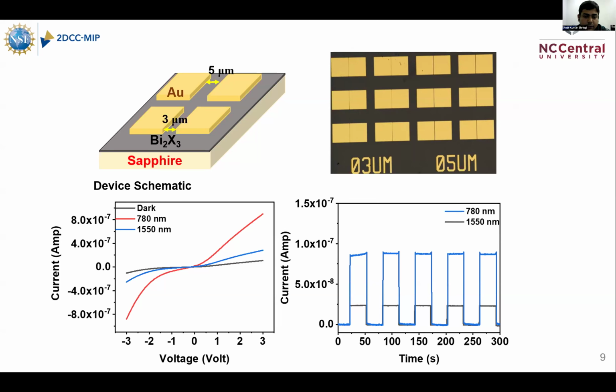The data shows that in the dark, the current was very low, somewhere around 10 nanoampere. But with 780 nanometer, we see a good photo detection current. The photocurrent for 780 nanometer was relatively higher than for the 1550 nanometer laser.